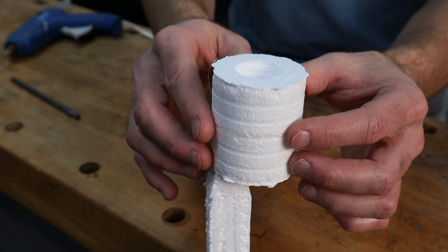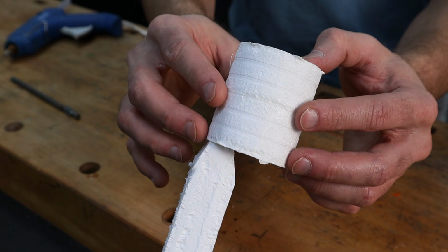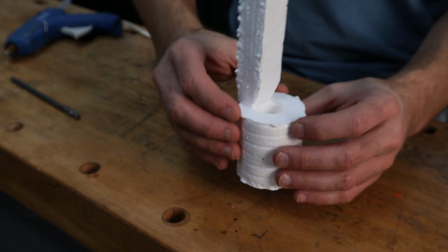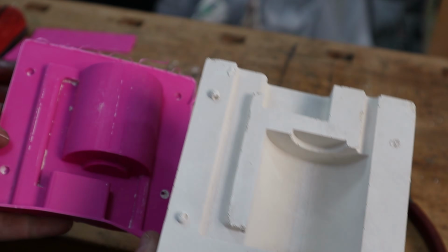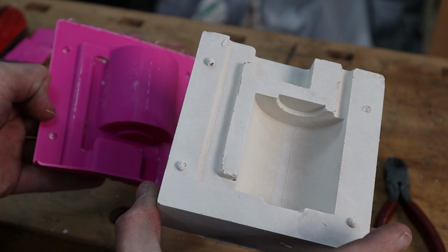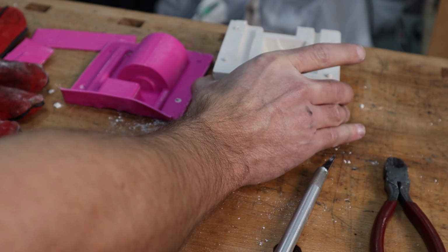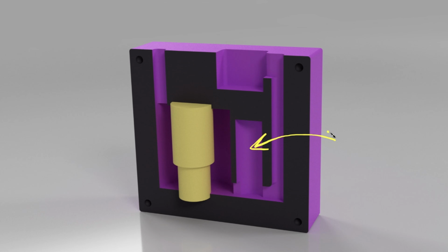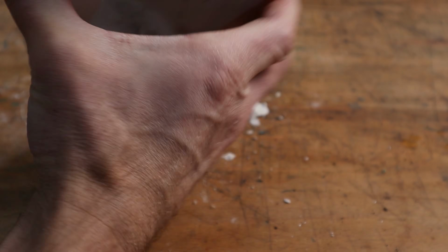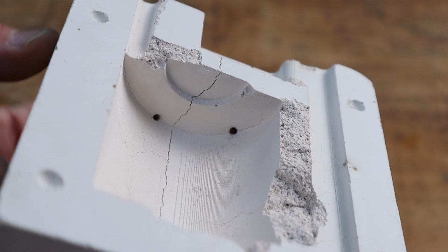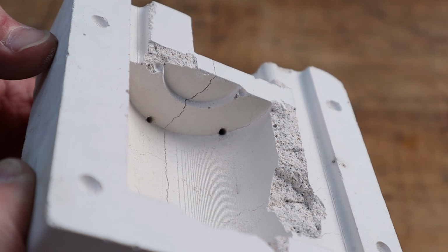If I'm in a pinch and I need a part right away, I think the lost foam method can work really well. But if I'm looking for parts that both look good and are more precise, the 3D print to create a plaster mold is a better option. I think there's still lots of room for improvement here too. I did not have a riser. The pouring basin might need to be a little bit bigger and a little bit of adjustment to the shape as well. And there needs to be some small vent holes drilled into the mold to allow some trapped gases to escape a bit more easily. The sprue and the basin should probably reach up a little bit higher as well.